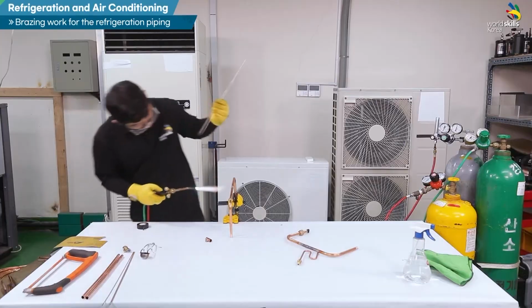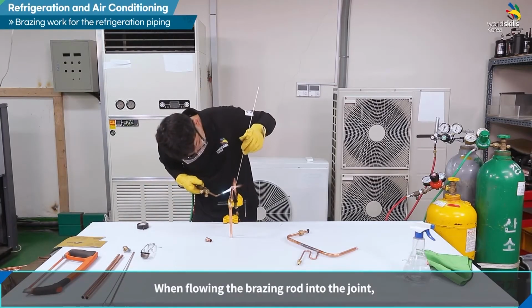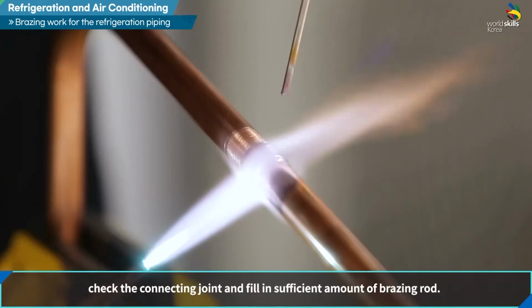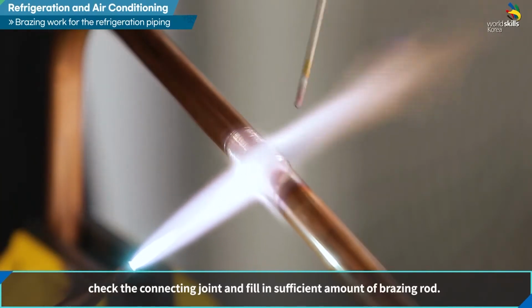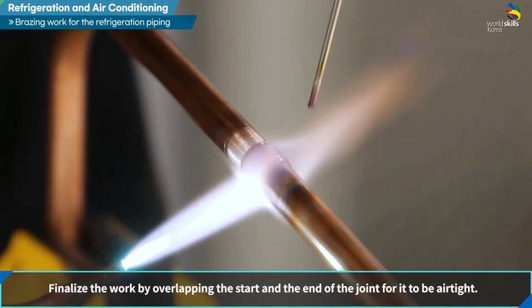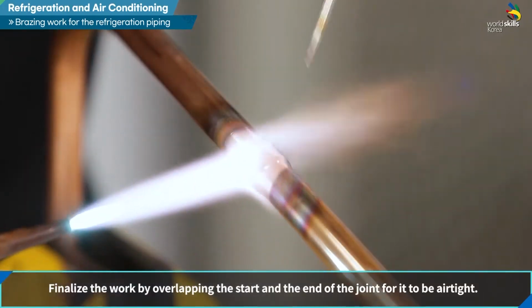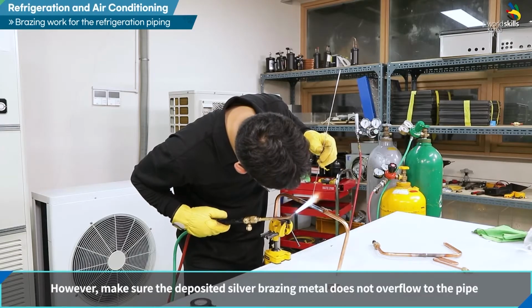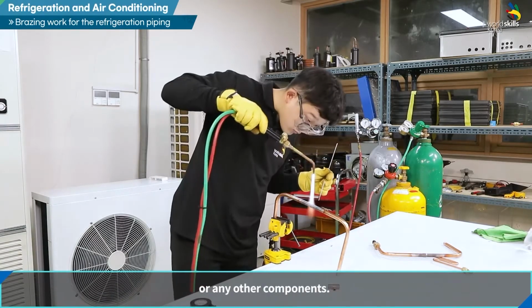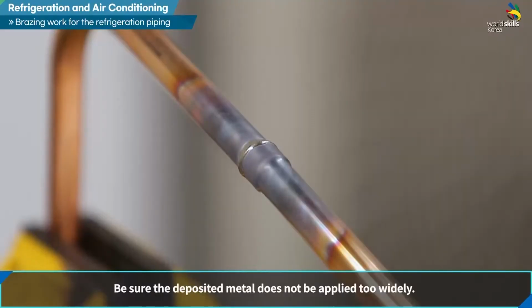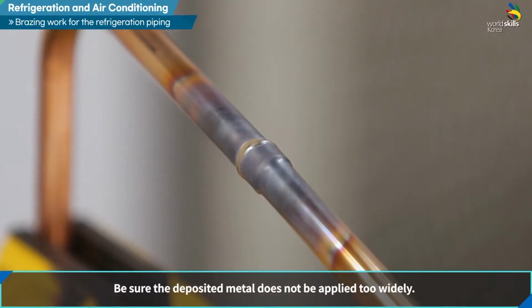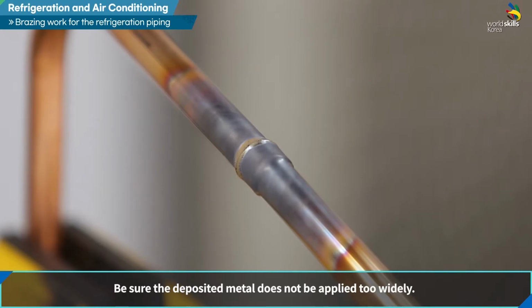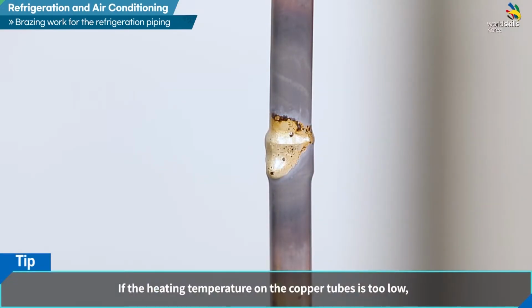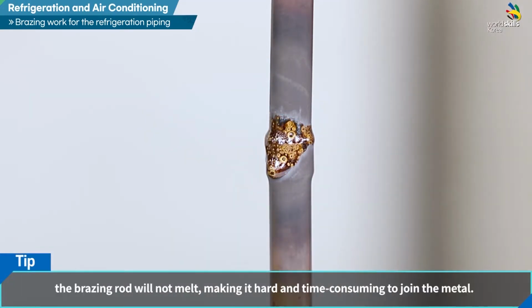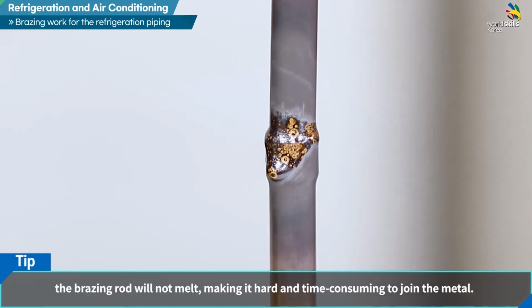When flowing the brazing rod into the joint, check the connecting joint and fill in a sufficient amount of brazing rod. Finalize the work by overlapping the start and the end of the joint for it to be airtight. However, make sure the deposited silver brazing metal does not overflow to the pipe or any other components. Be sure the deposited metal is not applied too widely. If the heating temperature on the copper tubes is too low, the brazing rod will not melt, making it hard and time-consuming to join the metal.